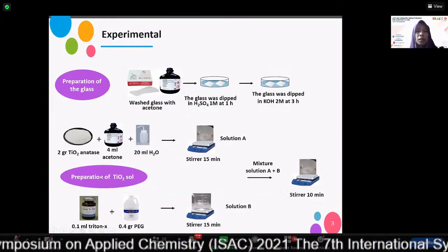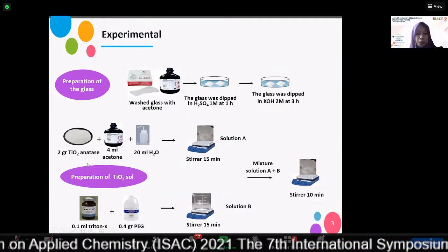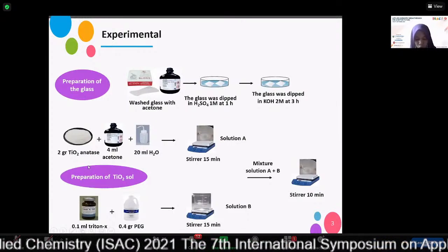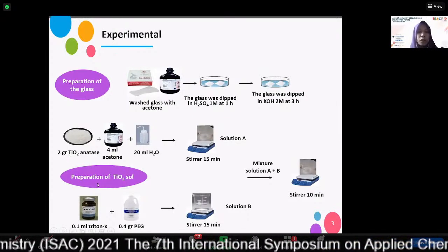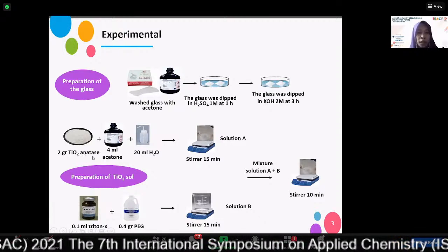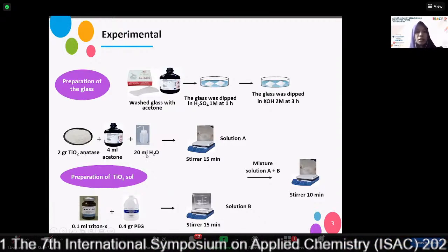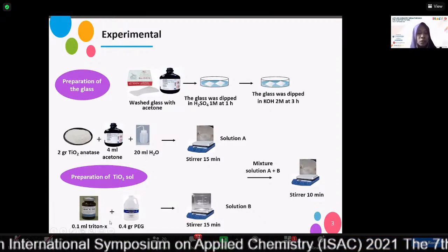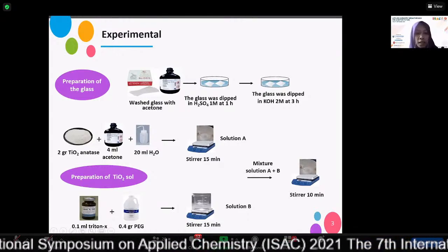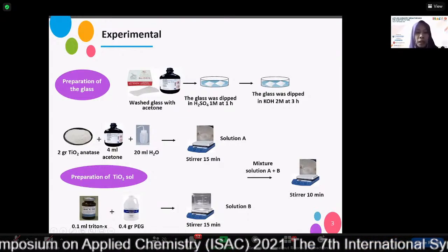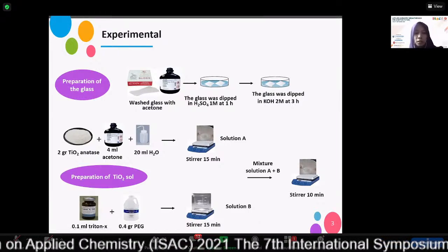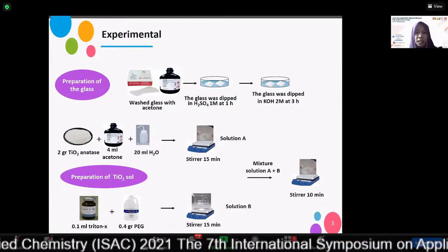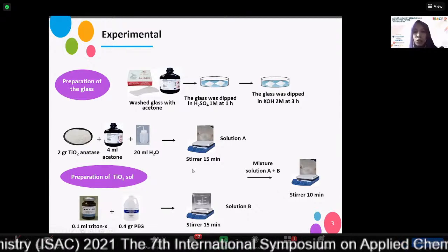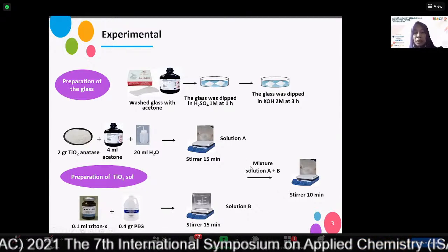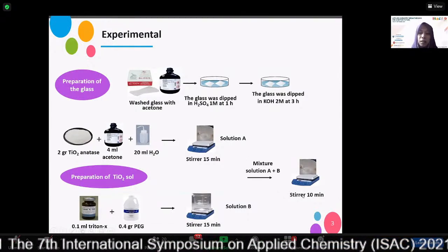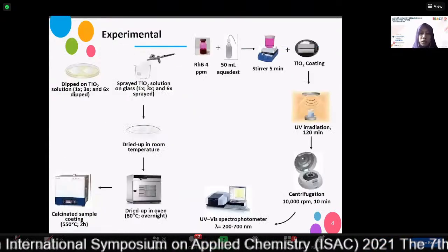The TiO2 sol was prepared using two solutions. First solution is TiO2 anatase with acetone and water, and the second solution is Triton X and PEG, polyethylene glycol. And then these two solutions were mixed to make a final solution.